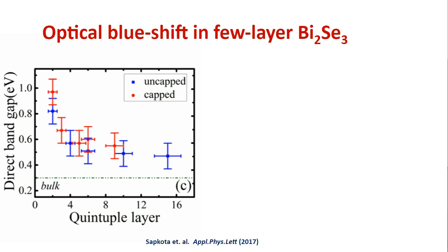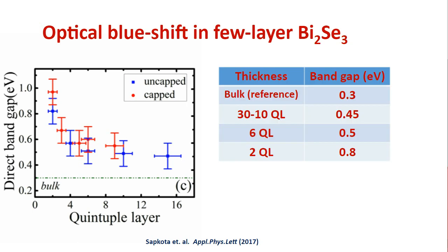So this is kind of the summary, right? Bulk bismuth selenide, I did not mention that, has a band gap of 0.3 eV. Now in all our samples, as high as 30 quintuple layer, we saw the band gap go as low as 0.45. 6 quintuple layer, as I was showing earlier, the band gap is around 0.5 and 2 is 0.8. So we do see two things happening here. One is, why don't we see a 30 quintuple layer or even a 10 quintuple layer show a 0.3 eV gap? So that is the first question. Are we overestimating the gap because of some instrumentation problem or an artifact or some systematic error, or is it real?